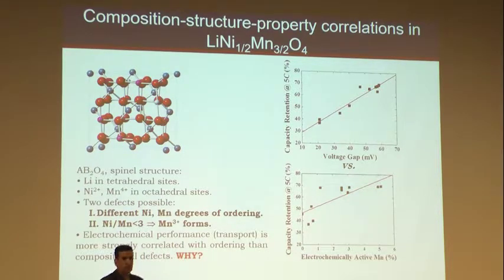This voltage gap has to do with the way that the voltage profile looks for this material. And I'll show you a couple of voltage profiles next. But just believe me when I tell you that the higher the voltage gap, the more disordered that material is. So if you plot that electrochemical metrics against these two chemical parameters, you'll see that the correlation is much stronger with structural ordering than it is with the amount of manganese 3 defects. And the question is why that is.